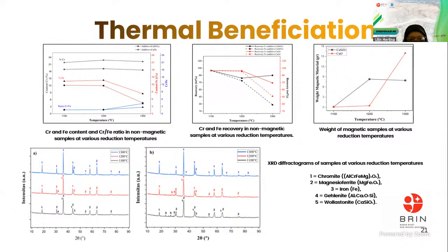This is the result of thermal beneficiation. I use several parameters, such as additive and reductor, and the last is temperature. The optimal is in temperature of 1100 and 1300 Celsius degree. The additive, the base is calcium silicate, and then the reductor is coke in 7.5%.